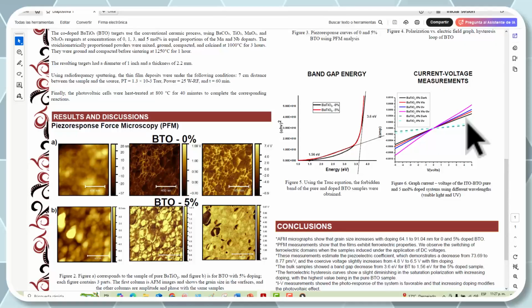However, when this same condition is applied to the 5% doped BTO sample, a greater increase is observed, starting with no illumination, then with visible light, then with UV light, and finally a more pronounced increase when both radiations are used. An improvement in the photoresponse property is observed.